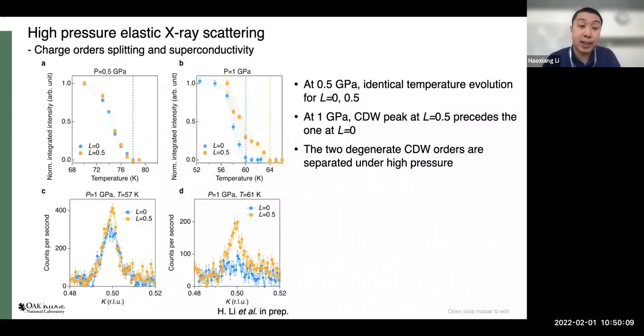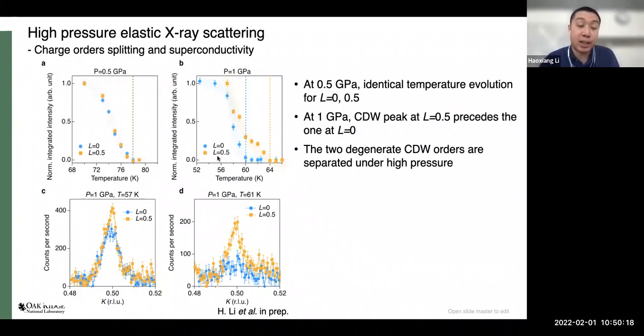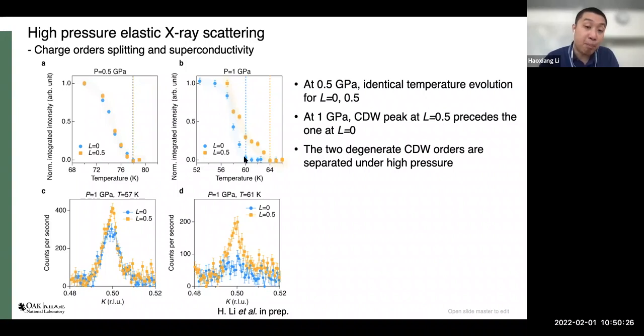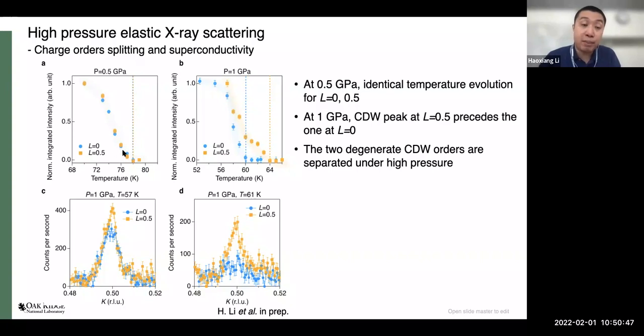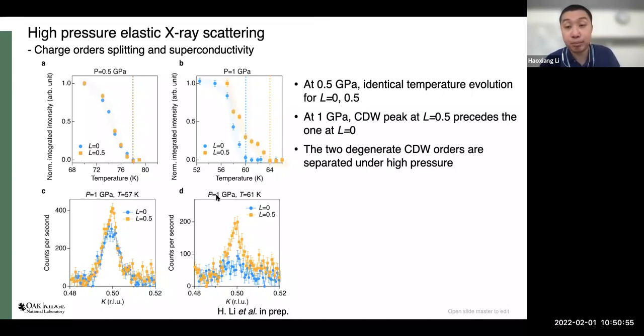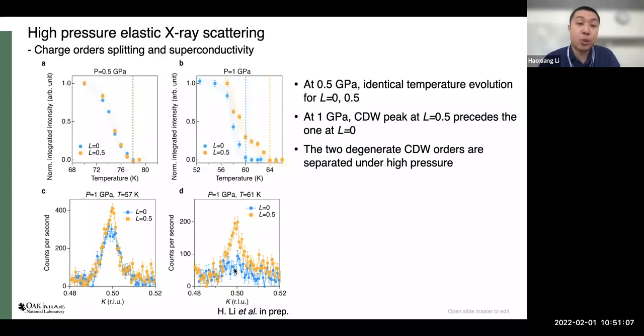More interestingly, we can actually separate these two charge orders by applying high pressure up to one gigapascal, which well separates the transition temperatures of the two orders by a temperature gap of four Kelvin. The blue order parameter is the L=0 in-plane CDW order, and the yellow one is the L=0.5 out-of-plane CDW order. At lower pressure (0.5 GPa), the two order parameters follow each other closely in temperature evolution. These two orders separating under high pressure is direct evidence of two distinct coexisting charge orders, rather than a single CDW transition with two scattering wave vectors.